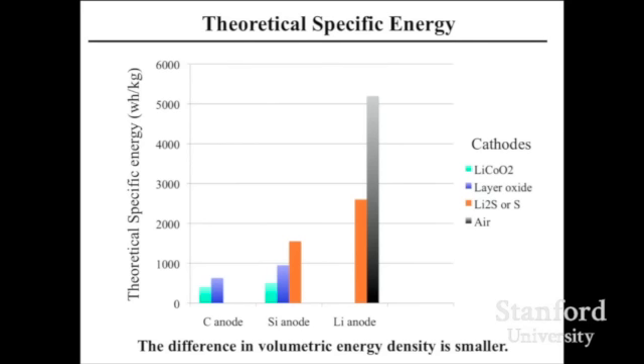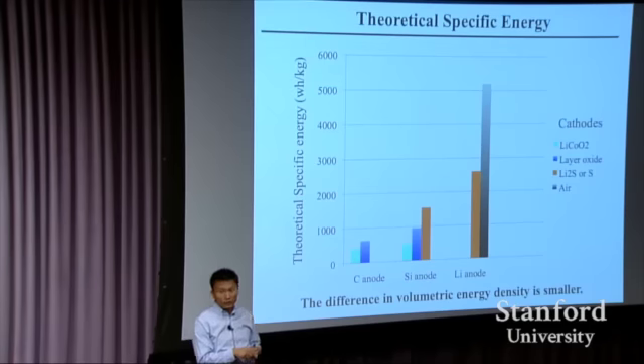But if you can make these materials work, this is a plot of energy per unit weight versus different anodes. Color indicates different cathodes right here. This is a theoretical one, only considering active materials weight. For current lithium-ion battery technology, you divide this number roughly by half. That's the real cell energy density you're talking about. So carbon with lithium cobalt oxide, this is used in your cell phone. You're talking about getting close to 180, 200 in reality. Theoretical is about 400.